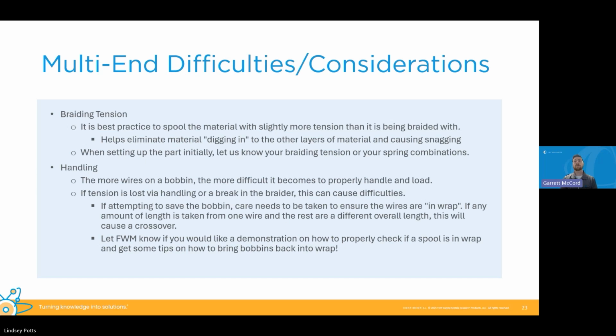Some difficulties or considerations to think about whenever you're first setting multi-end products up. The main one is braiding tension. It's best practice to spool the material with slightly more tension than you're actually braiding it with, which eliminates material digging into other layers, which can contribute to breakages during braiding. So whenever you guys are setting up your parts initially, going onto a braider, let us know your braiding tension or your spring combination so we can calculate the theoretical braiding tension so we can have our best chance for success from the start.